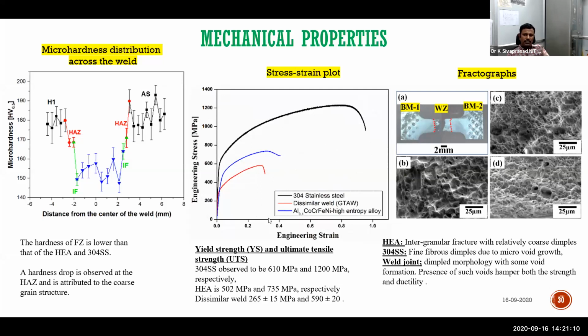That means it is cushioning. Whatever may be the loading condition, it is cushioning. And to say that our HAZs are not so weak, failures happened in the weld zone only, weld nugget only. And all the fractographs are evidencing almost a dimpled structure, which indicates a ductile failure. So even the weld joint is able to exhibit a good amount of ductility in the system.